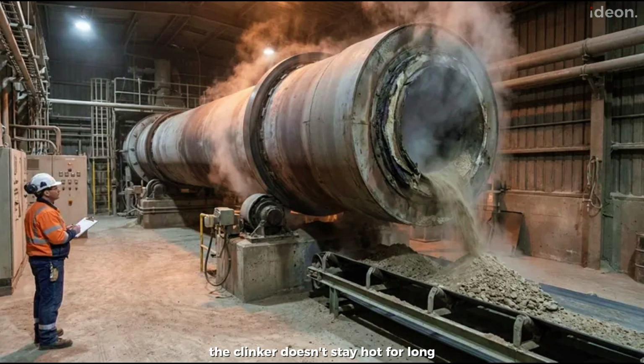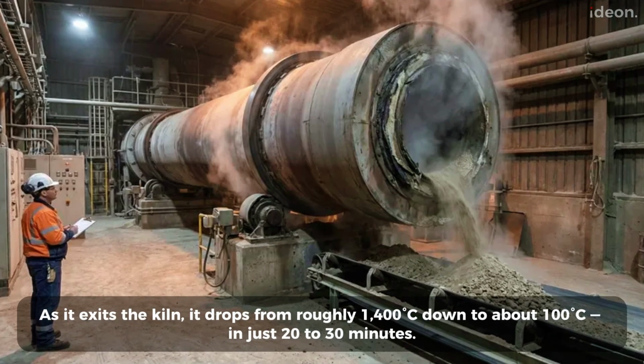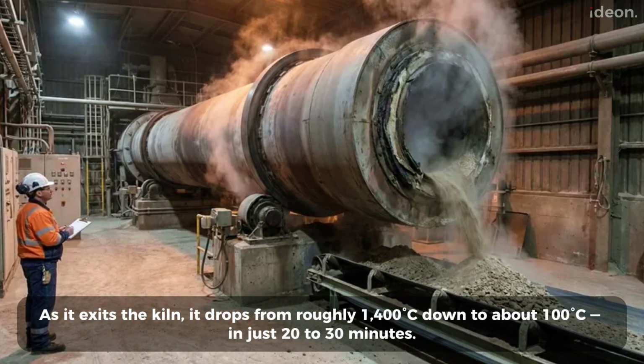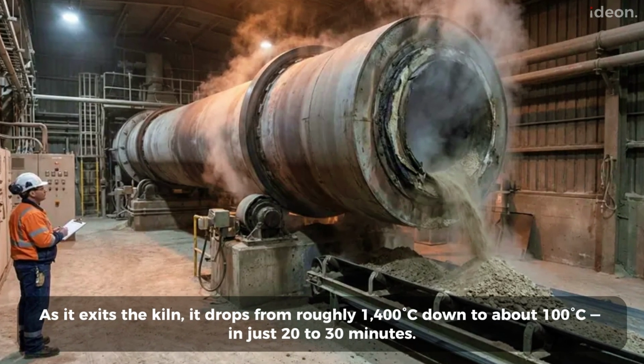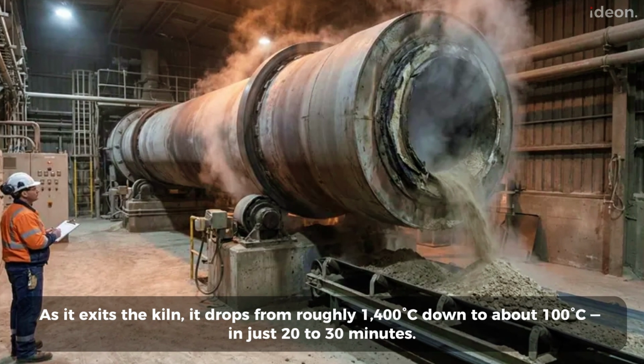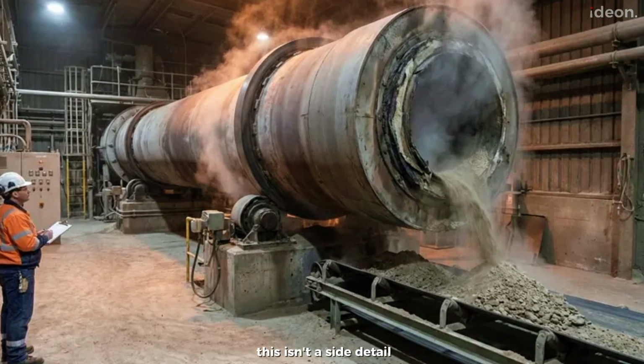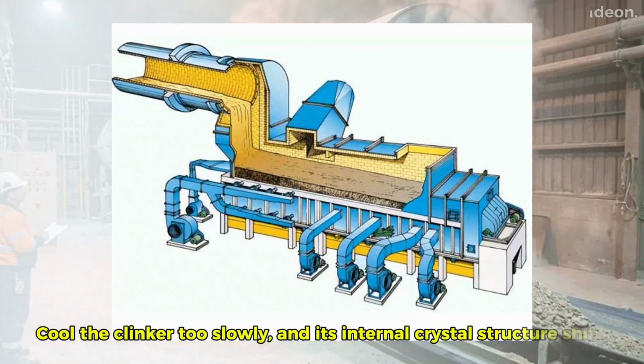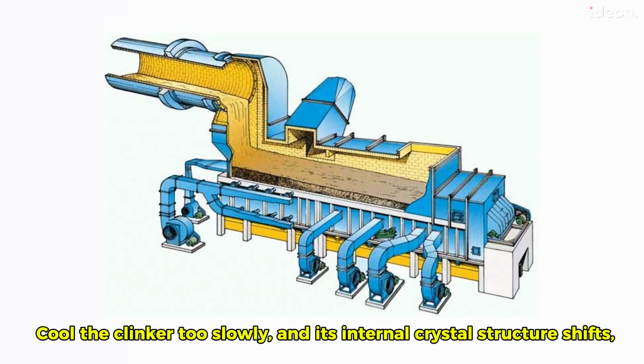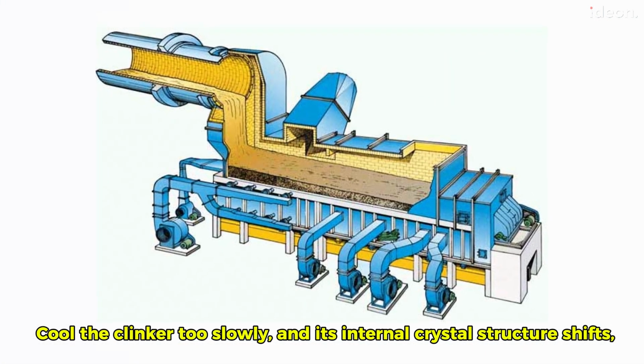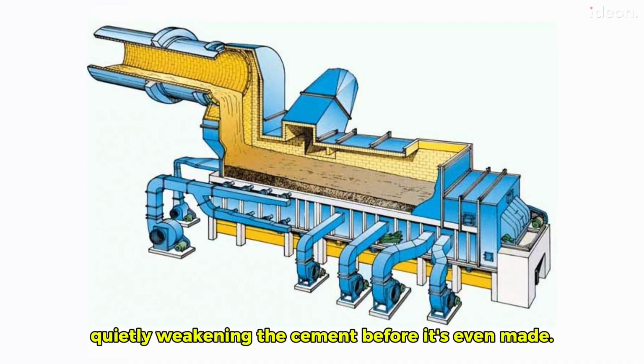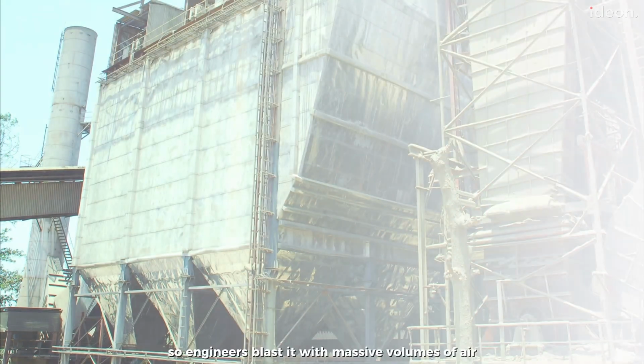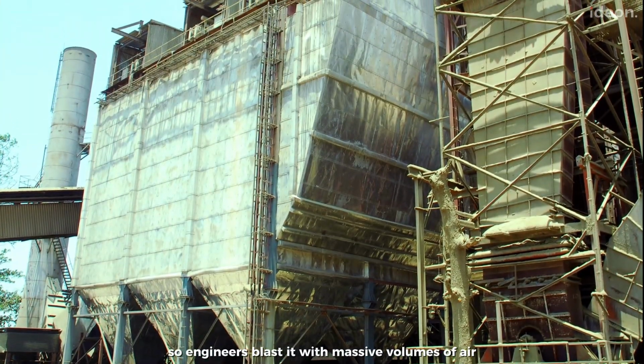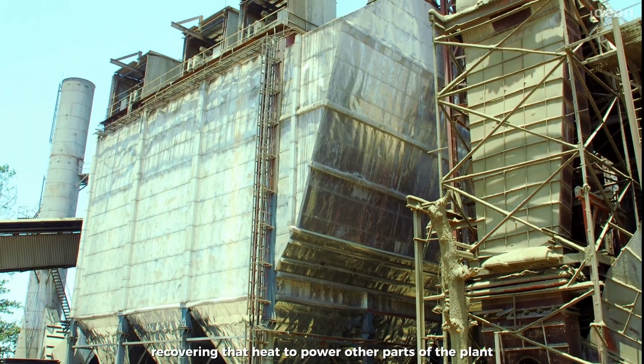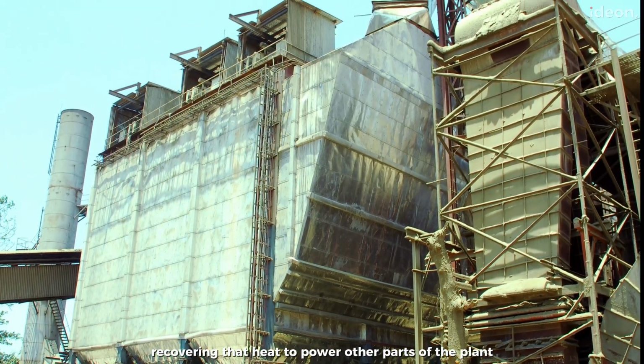Cooling, a race against time. The clinker doesn't stay hot for long. As it exits the kiln, it drops from roughly 1,400 degrees Celsius down to about 100 degrees Celsius in just 20 to 30 minutes. This isn't a side detail. It's critical. Cool the clinker too slowly, and its internal crystal structure shifts, quietly weakening the cement before it's even made. So engineers blast it with massive volumes of air, sometimes recovering that heat to power other parts of the plant.